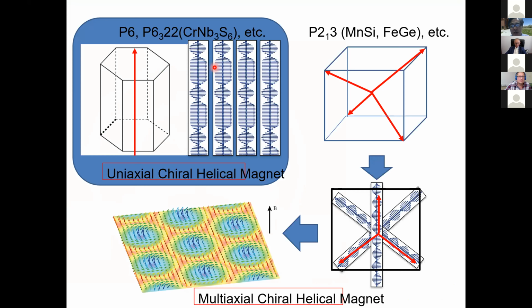There are several cases we can consider about topologically protected matter. This is our case. As I said before, the helical axis is only one axis, this is the P63 axis. The soliton is located in the plane perpendicular to the helical axis. But there are several chiral magnets already found in the P213 space group, manganese silicide or iron germanide. There are 4 helical axes. If we cut a plate from this sample, finally we have 3 helical axes. In this case, solitons run at 120 degrees to each other. Then we can get this skyrmion lattice.